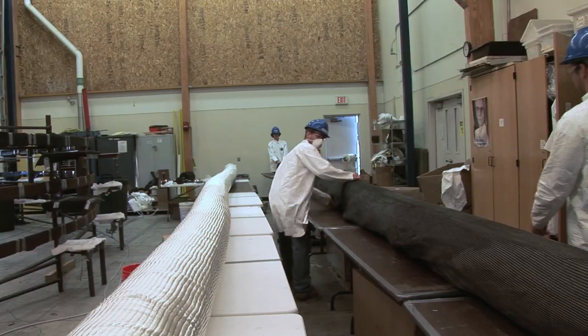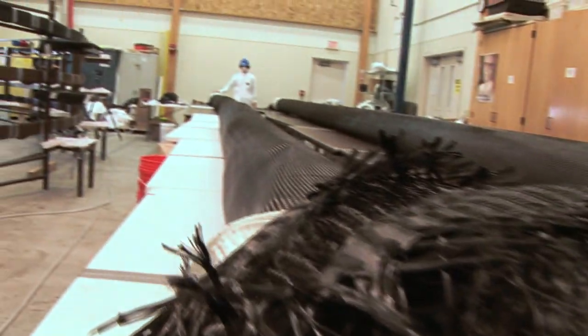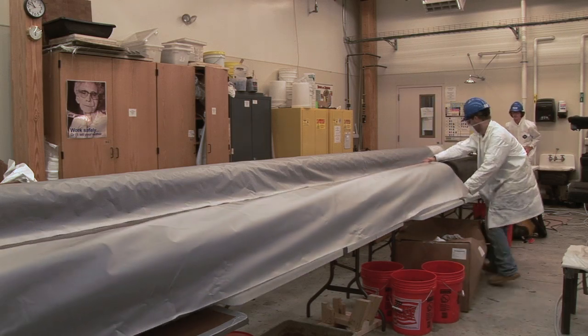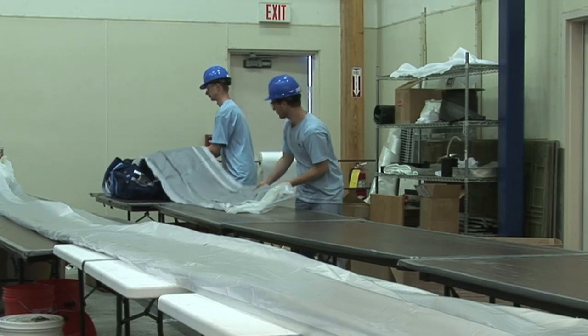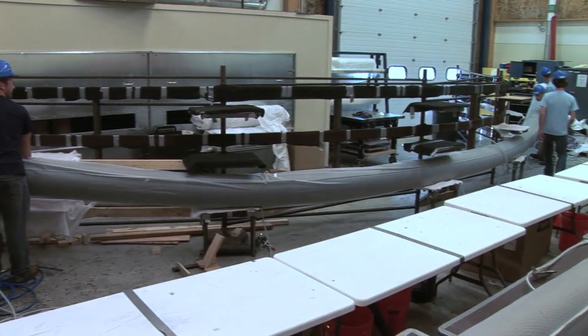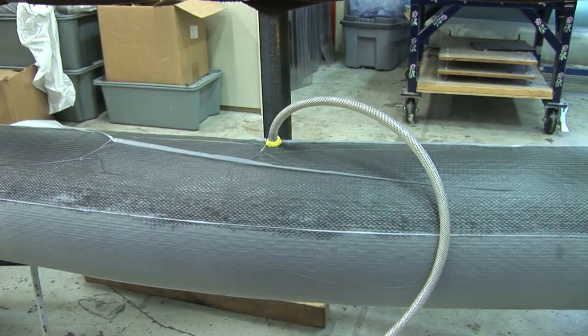The arches were constructed in the AEWC Composites Lab on the University of Maine campus, but for future projects it is expected that arches will also be fabricated at the bridge site. The arches will arrive rolled up to the site, will be inflated, placed over a mold, shaped to any geometry, infused with resin, and then allowed to cure or harden for three hours.